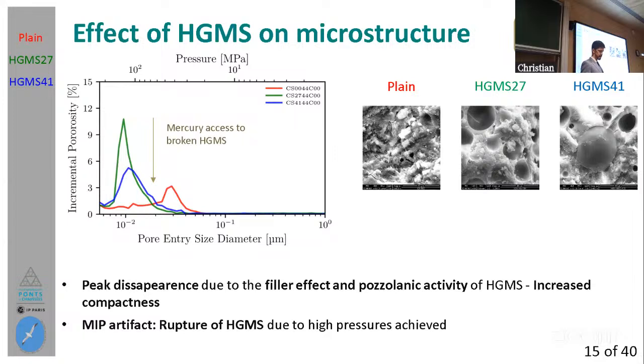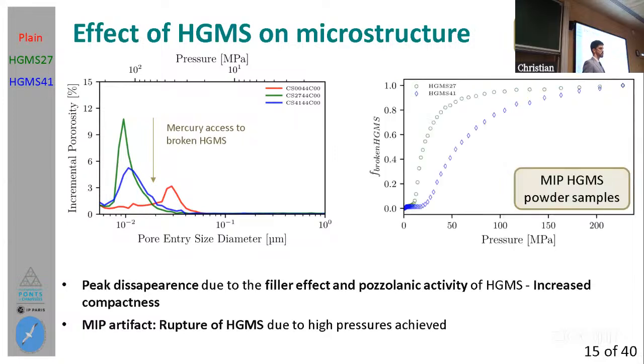Then you will notably see these two important big peaks that we have here for each of the cement pastes, and this is mainly related to the rupture of the spheres, which is happening due to the exposure in this MIP test, in which we are reaching high pressures. So what I have done here was MIP directly on powder samples of the HGMS, and I was able to see that they began breaking even before 50 megapascals. So this is around the pressure that is indicated here. This peak corresponds to the mercury accessing the void space inside the now broken hollow glass spheres.